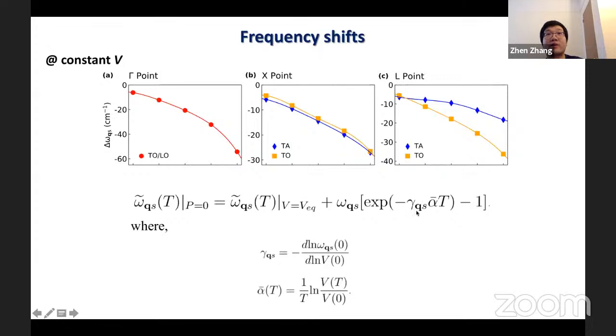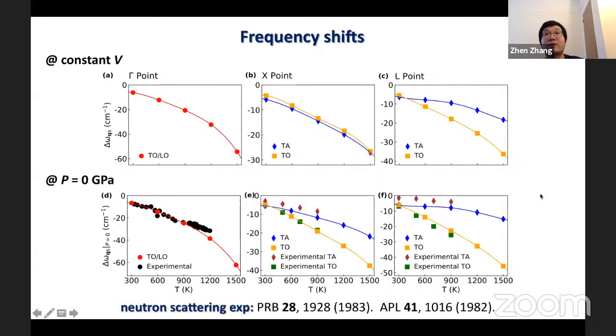Gamma QS here is the mode Grüneisen parameter, and alpha bar here is the average thermal expansivity. Then we can obtain the frequency shifts at constant zero pressure. The TO-LO mode at gamma point, the TA and TO modes at X point, and the TA and TO modes at L point all agree well with experiments.